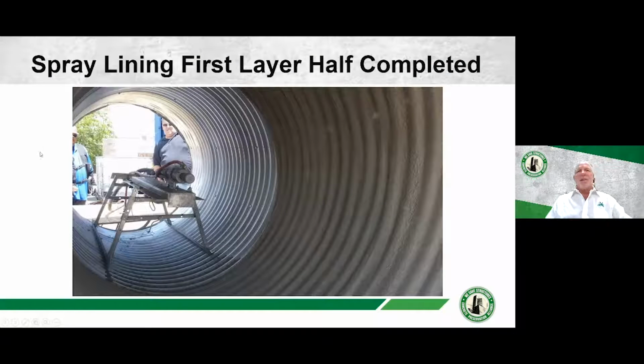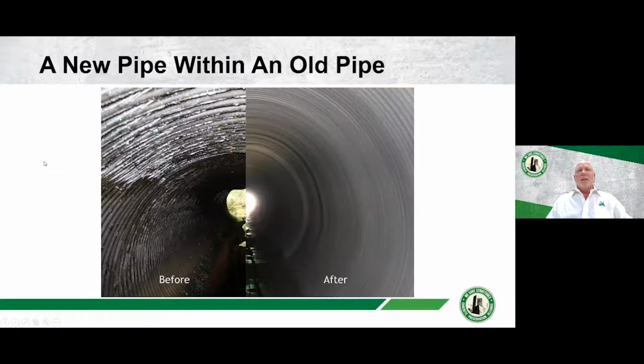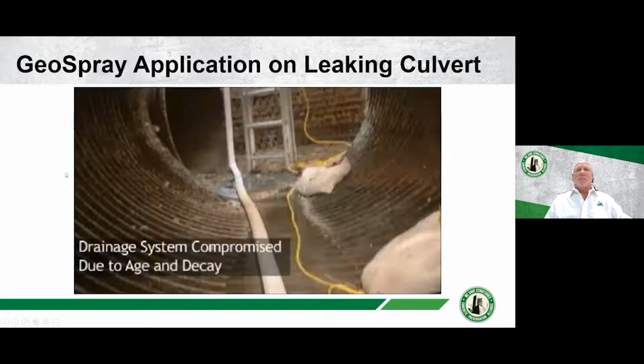Here's a quick look at the culvert that's about half sprayed. You can see on the right here sort of the consistency of what's going on. In this case, that's likely somewhere around half an inch of material being sprayed on. Quick before and after look at a pipe. On the left here, you can see the deteriorated pipe, and what you'll end up with as a final product with the spray applied lining system.